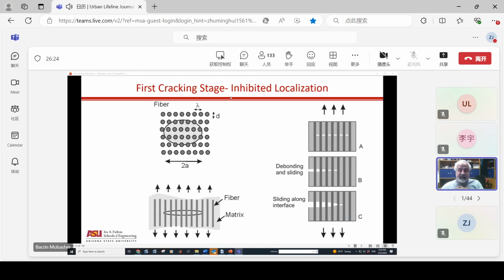Now, some of the examples, cartoons: if you have a small crack before it has localized, of size 2a, if it intersects a certain number of fibers, the only way you can deliver energy to the tip of the crack is by opening of the crack. But if the fibers are bridging it, then it doesn't allow these cracks to join each other, and it delays. And then when you go into debonding, you're going to have to slide these debonding zones, and that dissipates energy. The sliding and opening makes it extremely difficult for us to deliver energy to this point in the corner where it is being dissipated. So this is what I call inhibited localization.